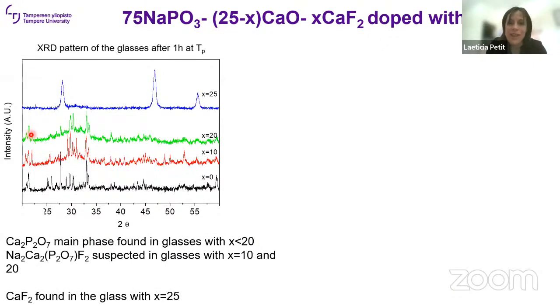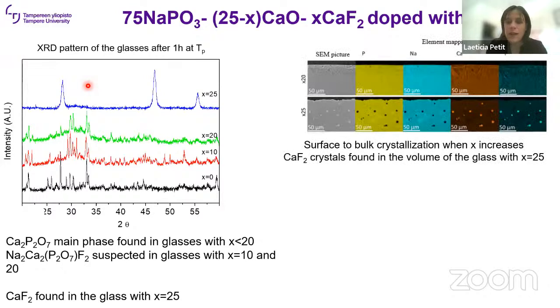So all the glasses with calcium oxide and calcium fluoride have different peaks related to the different crystals. But the glass prepared with 25 mol% of calcium fluoride exhibits only a few peaks, which are related to the calcium fluoride crystal. We used it again, and we found that we have this surface crystallization for all of the glasses except the one with pure calcium fluoride. And as for the other glasses, we have this calcium fluoride crystal growing, precipitating in the volume of the glass. So it's still, again, very promising.